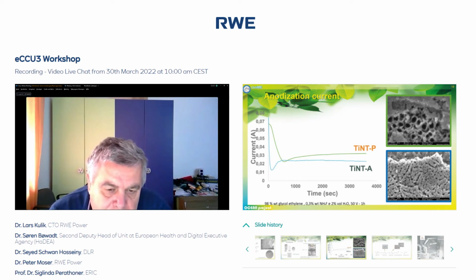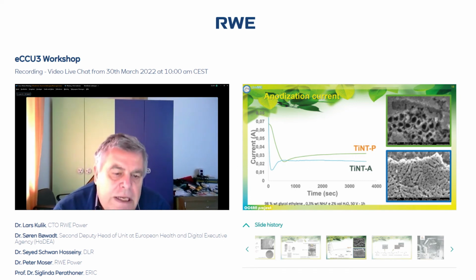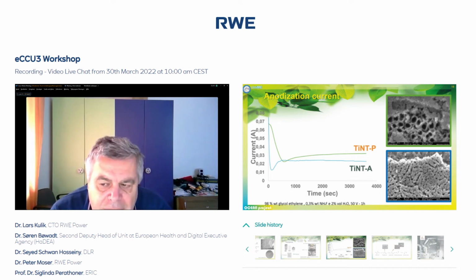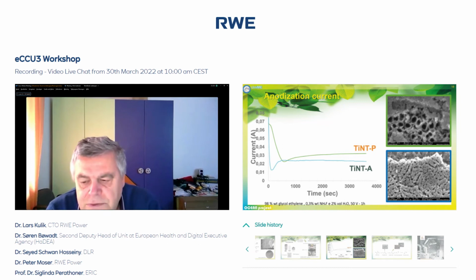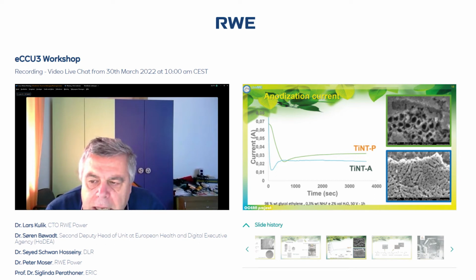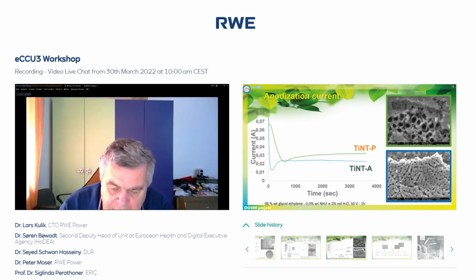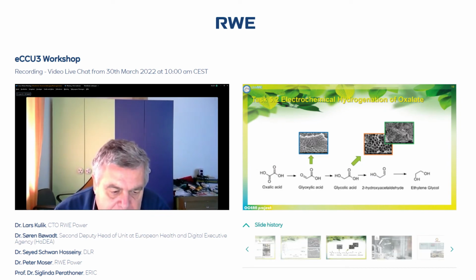So essentially, what is the process? When you start anodization, you first form an oxide layer, and this is the reason why you decrease the conductivity. Then you start to have a reconstruction of this layer, and you can have different kinds of reconstruction. You can form a kind of disordered layer, like you see in the bottom electron microscope image, or you form a more ordered array of titanium nanotubes on top. This of course depends on the conditions of preparation and how you optimize the different elements. So you have a variety of possibilities by controlling the preparation. And the next slide, number 19.